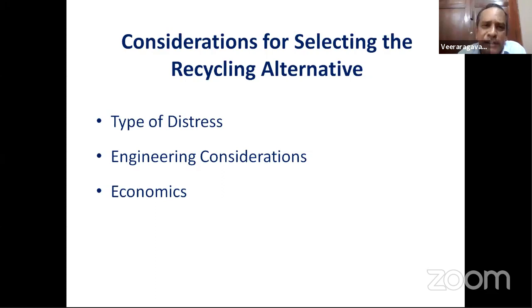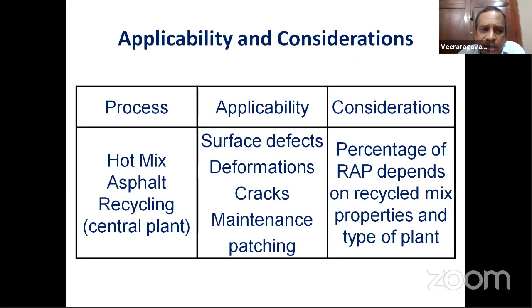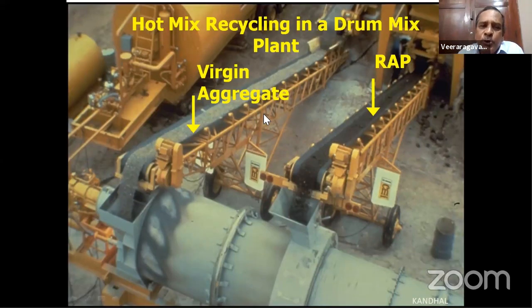On one hand, there is no other alternative as well because aggregate is not available. So you can go in for hot mix recycling in a central plant if there are defects in the surface, deformations, cracks, or maintenance patching. But the percentage of RAP depends upon the recycled mix properties. That's a catch there.